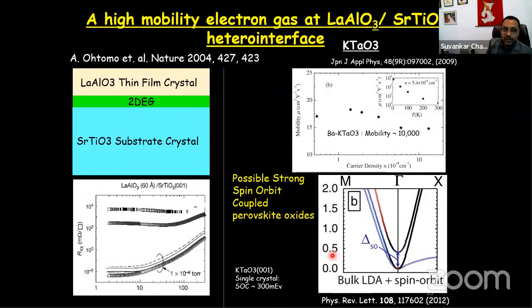So the idea of this two-dimensional electron gas at the interface of two insulating oxides is not new. In 2004, people had shown that if you make an interface of lanthanum aluminate and strontium titanate, both are insulating, but the interface becomes highly conducting. And it is the resistivity versus temperature data, where the resistance decreases with decreasing temperature, showing the metallic nature of this material. And it shows in the course of time many fascinating properties.